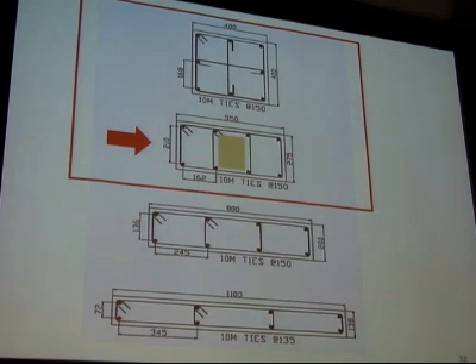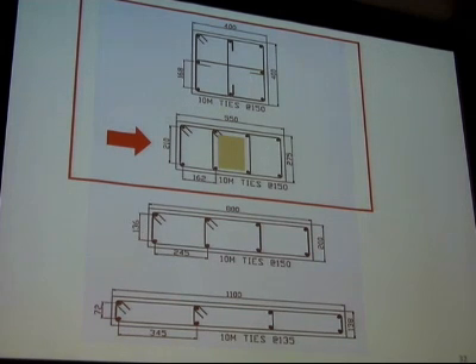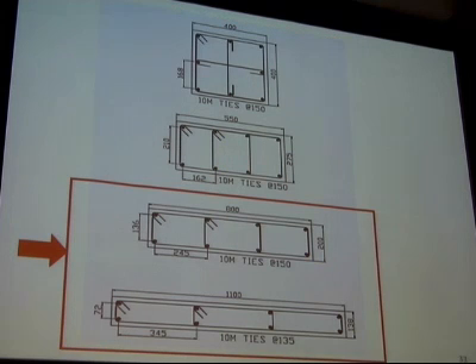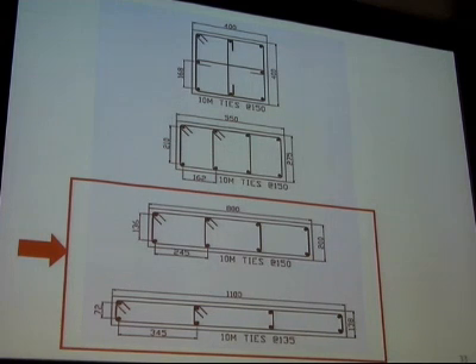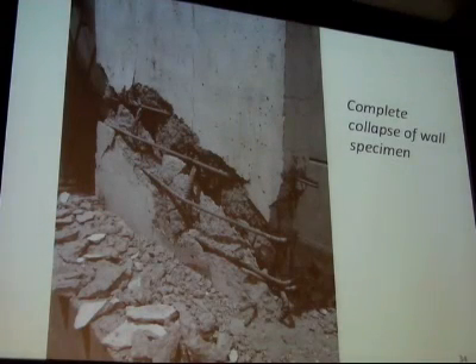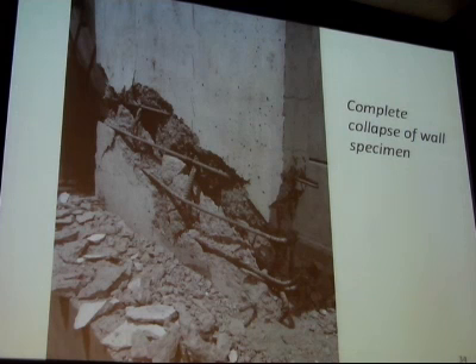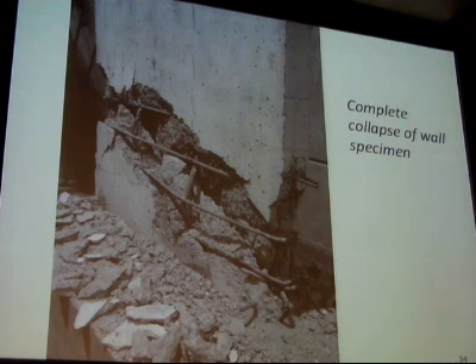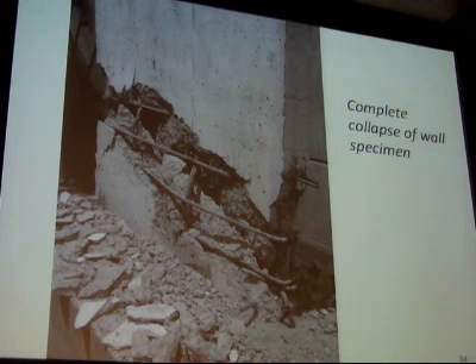But these elements have a certain dimension to them, like the square ones, or they have rectangular shapes where it's like no more than 3-to-1. Once you get to the slender walls, once you start getting to 4-to-1 or 5-to-1, it's a completely different animal. And what we see happening in those is exactly what we saw happening in those little element tests. And here's an example of the wall specimen. We're loading it up, a little bit of damage. All of a sudden it goes bang, and it's gone. Complete load capacity is gone, and the failure mechanism is exactly like that element. It goes right through the thin wall and completely loses all its axial capacity.